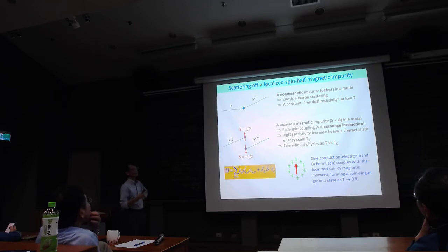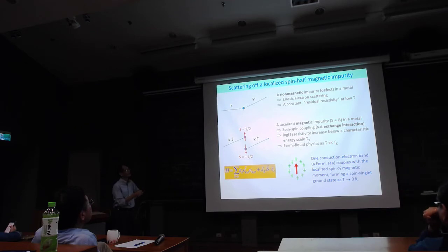And if you cool it down to a very, very low temperature, when there are no phonon vibrations, the resistance will come from this elastic scattering. And so we have a constant resistivity. We call it residual resistivity.